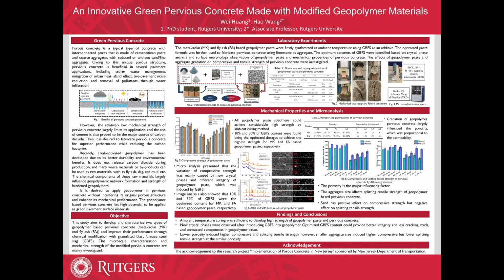new phases. We also did the SEM test on the geopolymer paste specimens, and we can see here there are several defects such as voids, cracks, and unreacted particles. So we transform the SEM images into binary images, and we use the white area to denote the defects. And we use the image analysis tool to calculate the total defects area. The results are listed here.